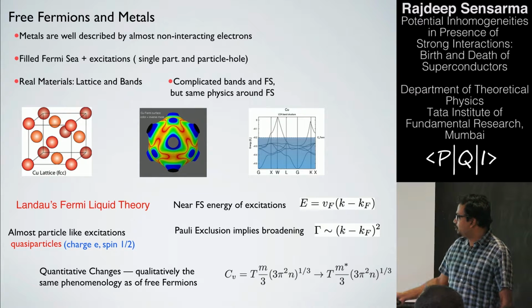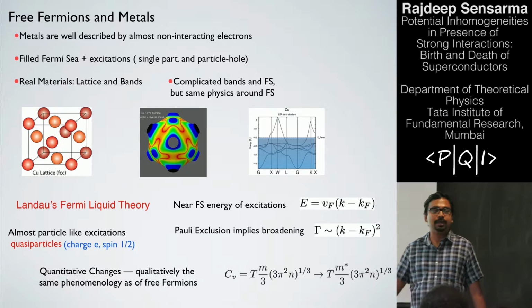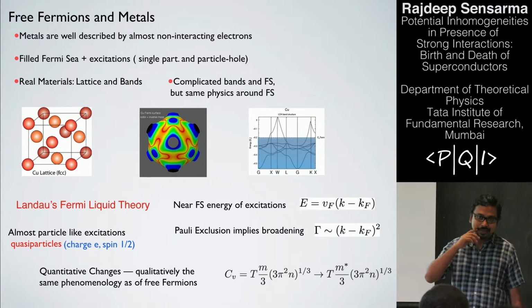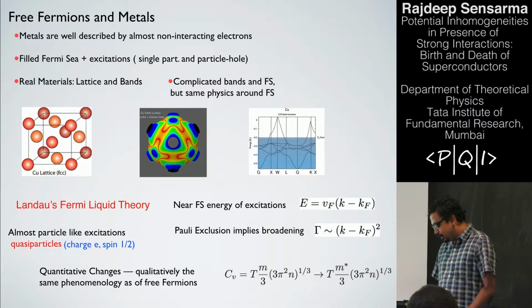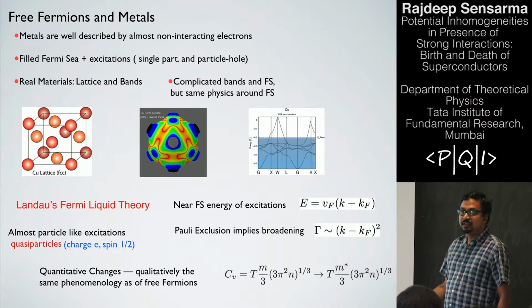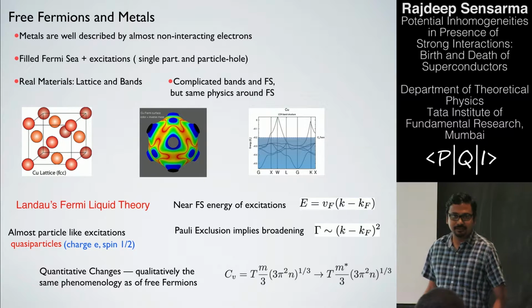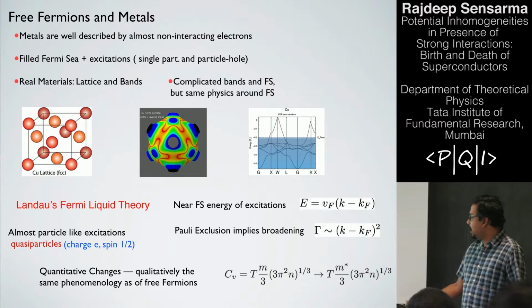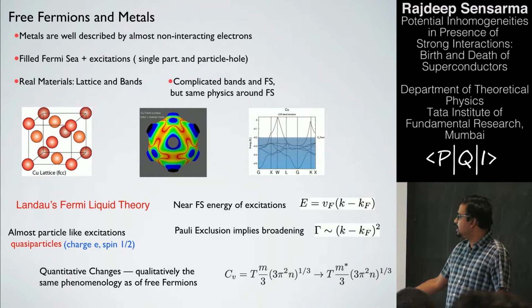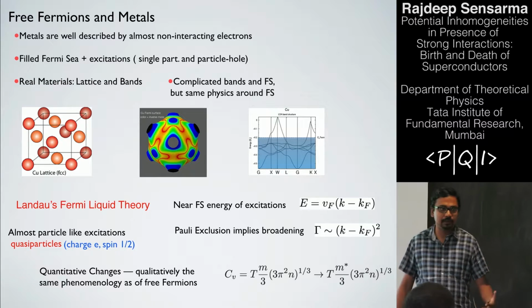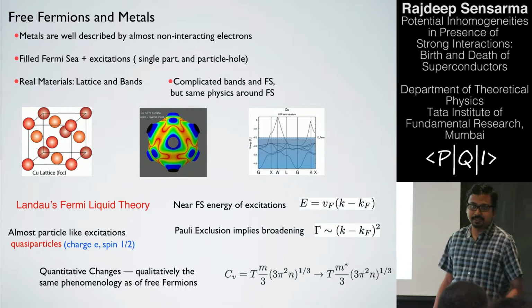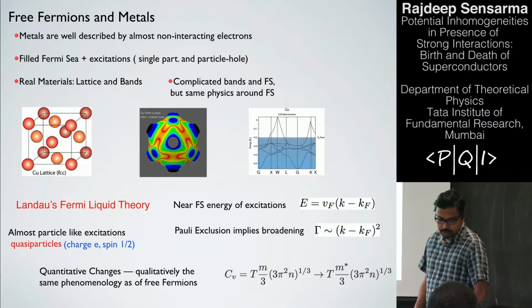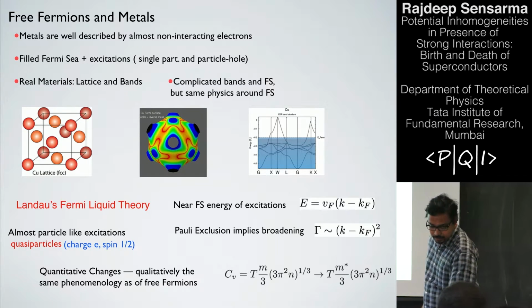These have charge e, spin half, and then you can try to make a weakly interacting theory of these almost particle-like excitations, or quasi-particles, and this leads to quantitative changes from a theory that you would have calculated with free electrons. For example, in a free electron theory, you know that the specific heat goes linearly with temperature with some coefficient. If you have Landau Fermi liquid theory, it again goes linearly with temperature with a different coefficient, m star. So quantitative changes come into the picture, but qualitatively the picture is essentially the same as the free electron gas. So that's why metals are essentially well described by a free electron gas.